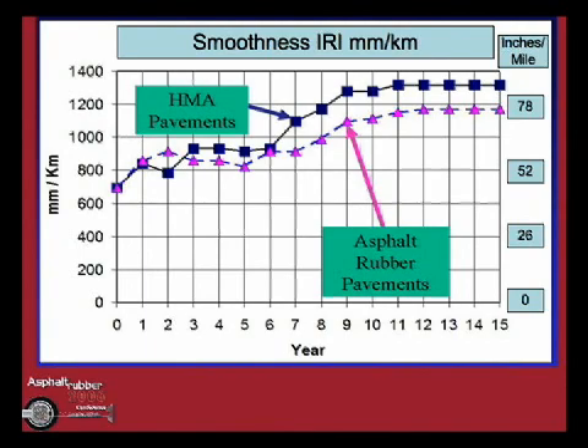Smoothness has been very good over the years. This is inches per mile, which many of you in the audience are probably more familiar with than millimeters per kilometer. And you can see that oftentimes in Arizona we have projects that start somewhere around 40 inches per mile by IRI, or even sometimes even less. And you can see the rubber sections do quite well over time.